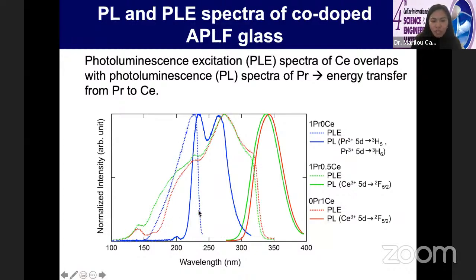So for us to excite the praseodymium in the glass matrix, we need excitation from 150 to 200 nanometers. Then we get this photoluminescence emission from praseodymium. Looking at cerium, it's this red curve.